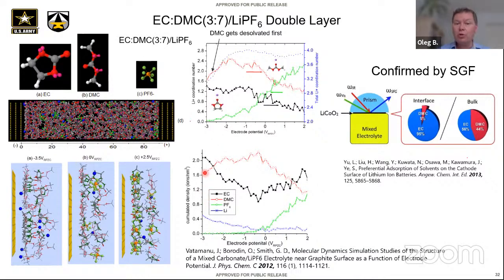Now, what about just overall species? Because lithium coordination is more important here, but the presence of just overall free EC, DMC next to PF6 is more important for the cathode, right? So now we are looking at just the cumulative density of solvents inside of the inner Helmholtz layer. In this case, we do observe that as potential gets increased from the potential of zero charge, DMC gets out of the first layer. It's pushed out by EC because EC has these carbonyl groups, right? It can rearrange its dipole and push out a not very polar solvent, and of course anions come in and also primarily push out DMC. That was very interesting and tells you that the actual structure at the cathode interface is quite different. That was reported a while ago.